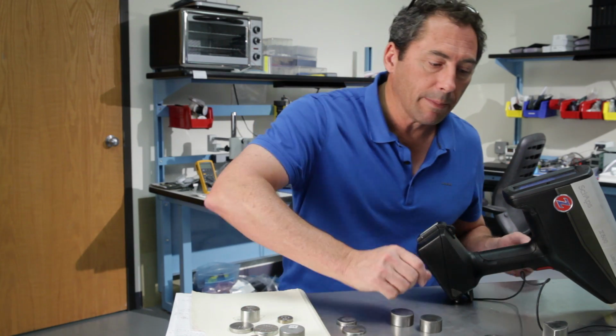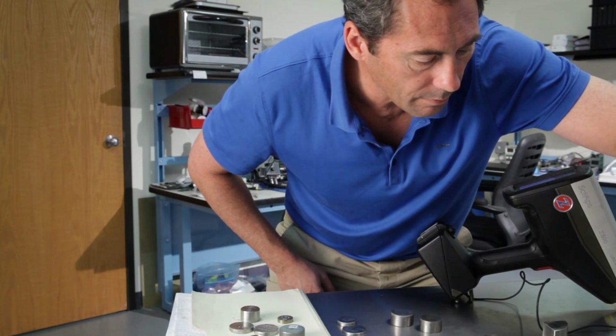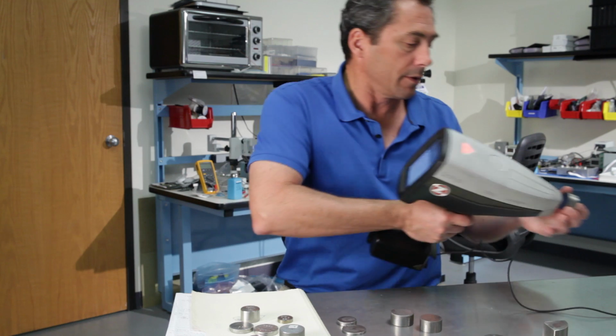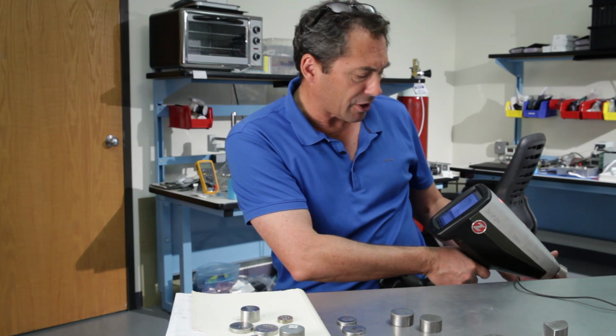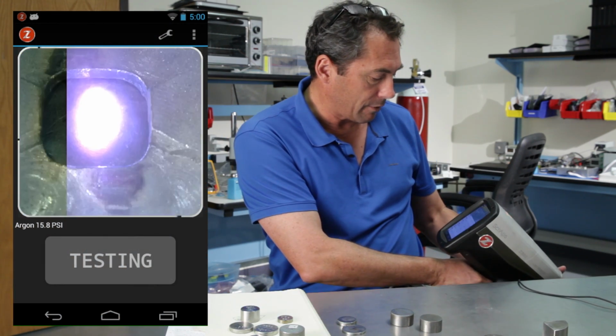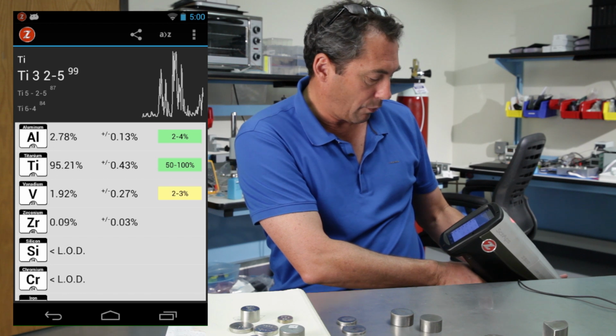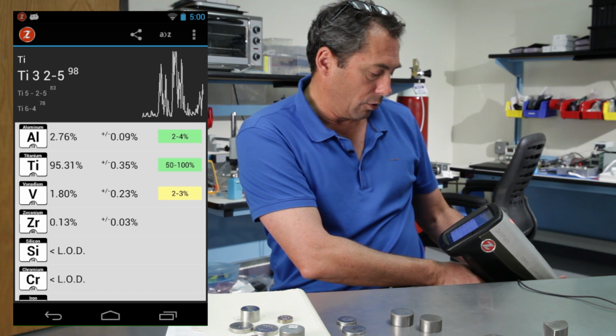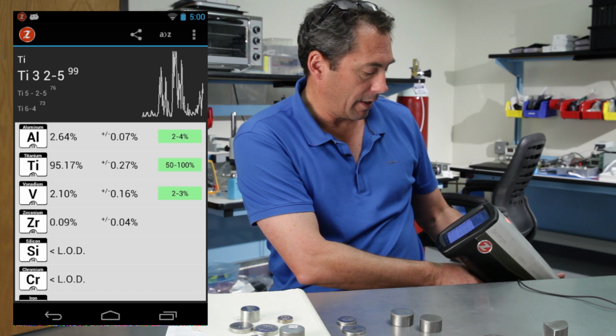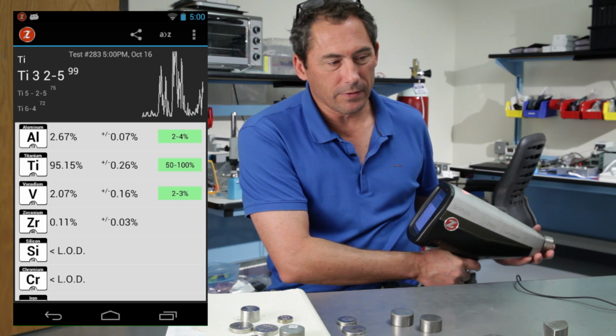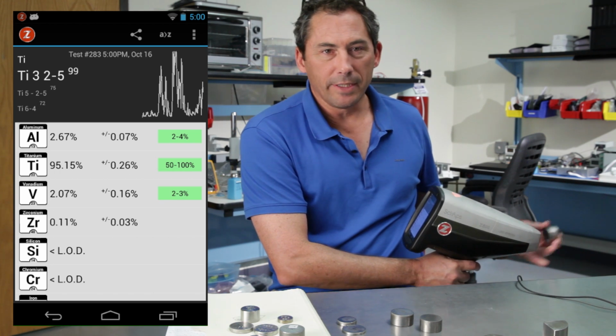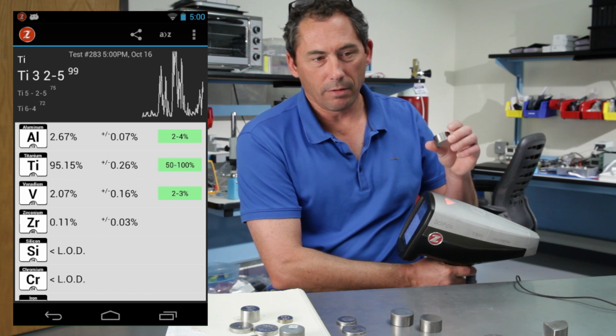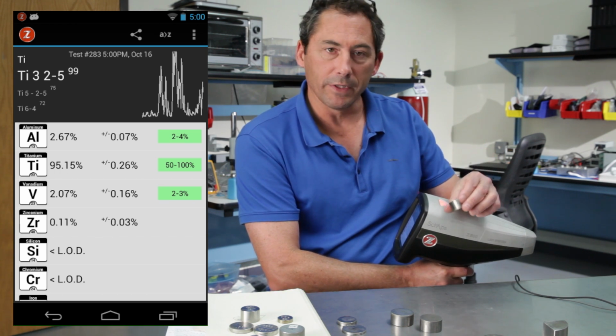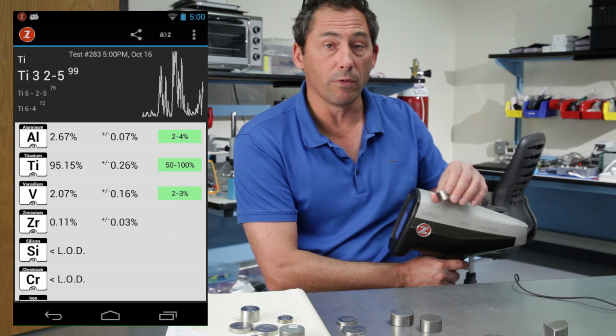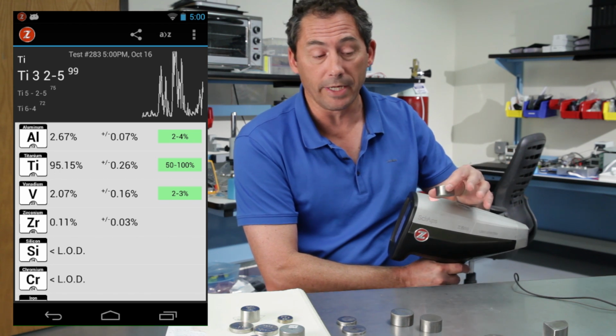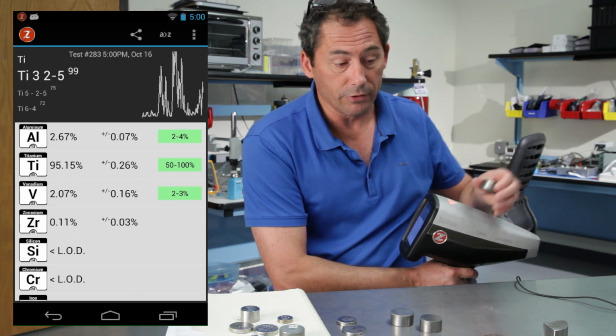Let's move on to a couple of titaniums. One I like to show is not such a common Ti alloy. It's 325, will come up in a second here. It's 3% aluminum, around 2.5% vanadium. That's an important one because a good LIBS unit needs to be able to distinguish the 325 Ti alloy from the very common 6-4 Ti alloy, which is 6 aluminum, 4 vanadium. And this one does that very well, as you can see.